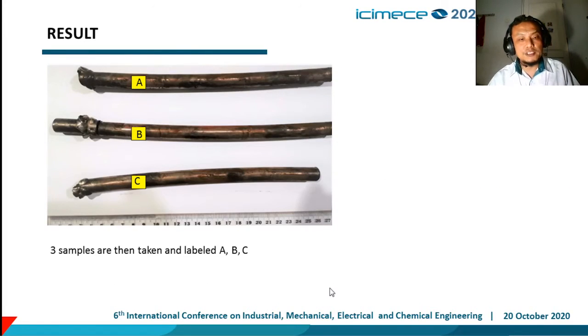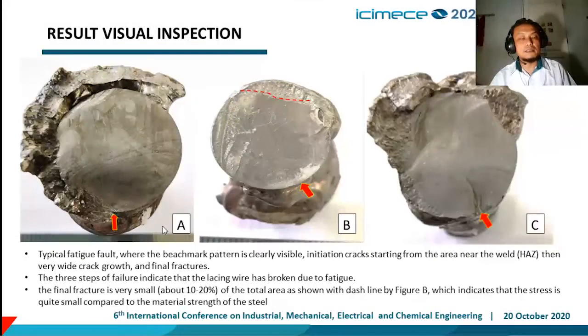So we took three samples labeled A, B, and C. This is the result of visual inspection. Typical fatigue fracture where the beach mark pattern is clearly visible, with initiating crack starting from the area near the heat affected zone, then very wide crack growth, and a final fracture. The three steps of failure indicate that the lacing wire has broken due to fatigue.